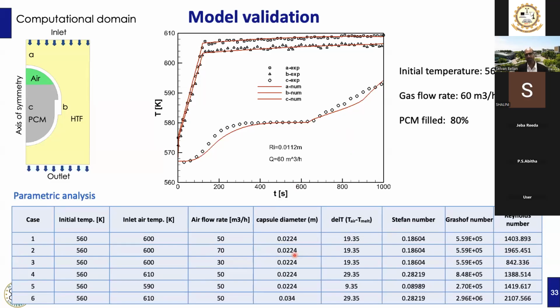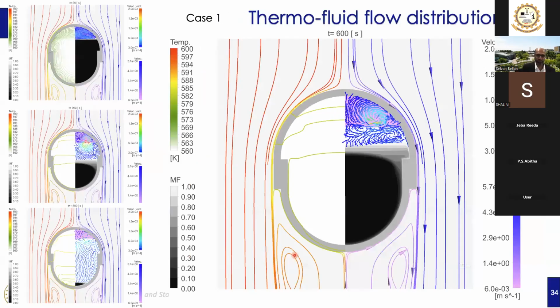This slide shows the thermofluid flow distribution of the capsule and the heating chamber for a typical case. As you can see, the left side of the heat transfer fluid domain shows the temperature distribution, and the black and white gradient color represents the melting behavior and the melt fraction. On the right-hand side of the heat transfer fluid, the streamlines represent the velocity of the gas. And this velocity vector represents the velocity distribution of the molten phase change material flow inside the capsule.